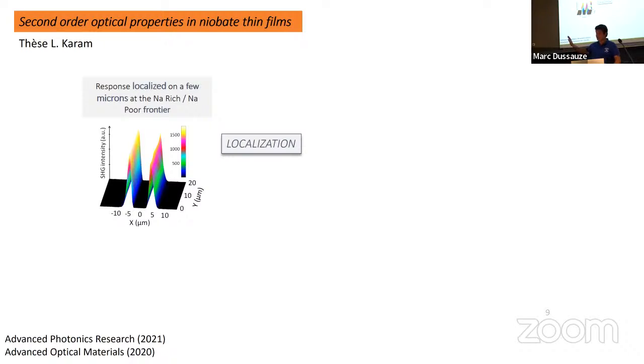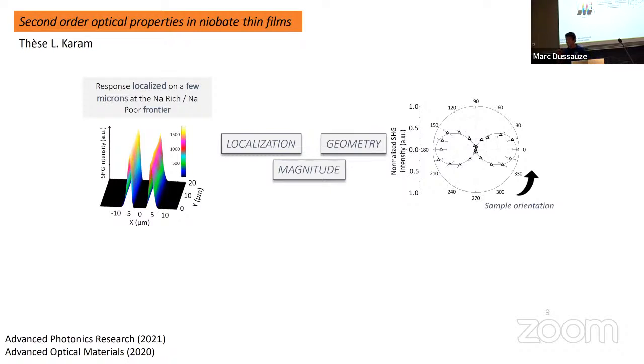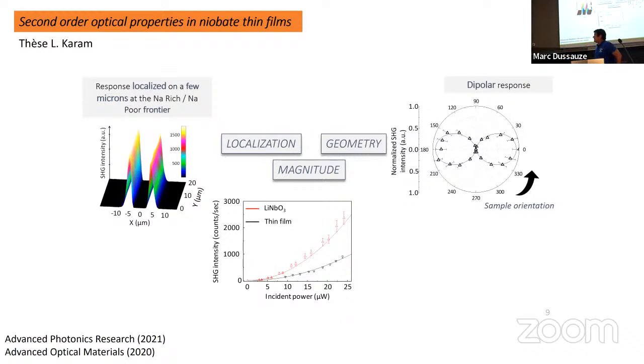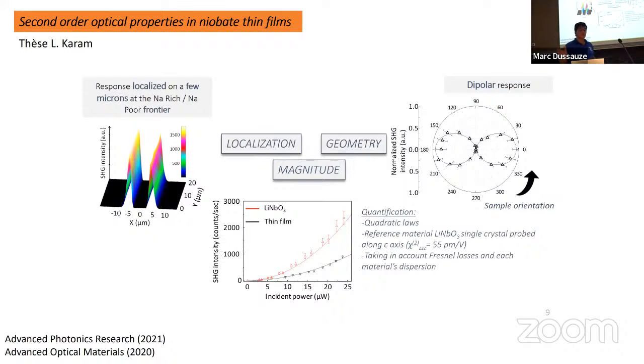So I've shown you the localization of the nonlinear response. That's very interesting. The second thing is the geometry. The geometry is purely uniaxial, so that's very good also. I told you we have 3 orders of magnitude, but we can completely erase this signal if we turn the sample. So it's purely uniaxial, and that's very good for applications. And now, since it's a quadratic response, we can compare the quadratic law for the single crystal lithium niobate and for our thin films, and we can see that we reach the order of magnitude of these very well-known crystals, almost 30 picometers per volt for these thin films.